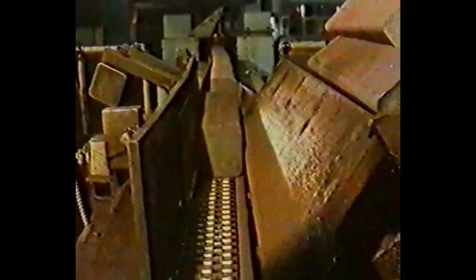But the big advantage of pressing over drop forging is that the piece is worked uniformly throughout the metal, compared with drop forging, where the impact tends to be confined to the surface. This can be important when forging large components like these diesel engine crankshafts. They start life as 140-pound billets cut from a length of steel bar. Then they're heated to the forging temperature of 1260 degrees centigrade in an induction furnace.